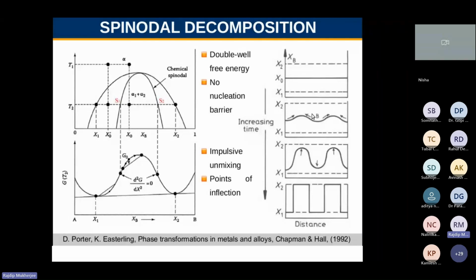And inside the spinodal, you can also see the uphill diffusion that I have talked about. So when the phases decompose, the atoms can move from lower concentration to higher concentration as well. And this cannot be solved using Fick's law. That is why we use the Cahn-Hilliard equation that I showed you, which is similar to a diffusion equation, right? Okay, so next, this is a textbook, the Porter and Easterling book, where you can see this kind of phase separation. You can read about it.